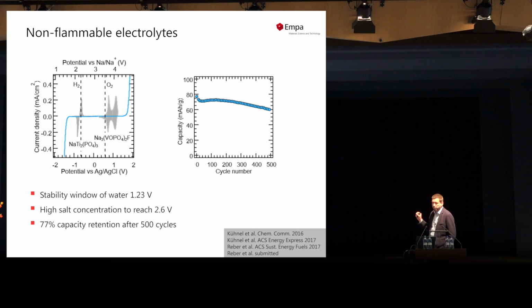We think that it's important to use sodium in this case because we use very high salt concentration, so we don't want to use lithium, and we believe that this also could reduce the cost of the assembly because you don't need any inert atmosphere to assemble these cells because they are basically stable also in humid environment. So David received the poster award at the ECS Spring meeting this year for his work, and also pitched his project at the Falling Walls Lab, the Swiss qualifying, receives here the first prize award from ETH Vice President of Research Detlef Günther, and will represent Switzerland now at the global finals of the Falling Walls Lab competition in Berlin coming up in November.